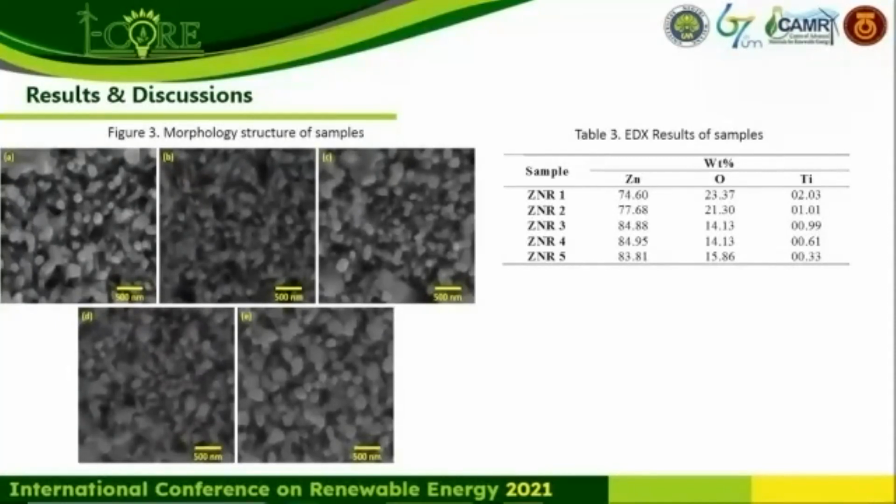in variation 5 hours. The decrease in weight percent in the fifth sample may be due to the hexamine composition during the hydrothermal process, which functions as a kinetic buffer for the pH of the solutions. It was caused by the initial process in the hydrothermal method that zinc 2+ ions and the pH level of the precursors were almost identical, but as the growth time goes on, the concentration of zinc 2+ ions will decrease and the pH of the precursors increases.